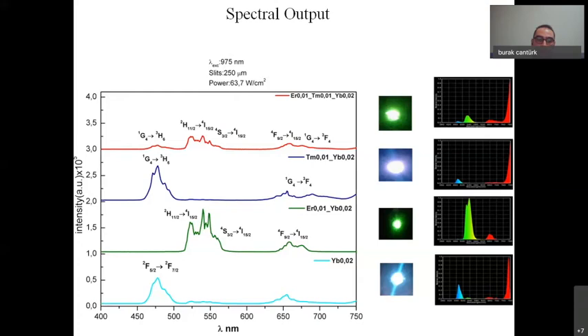As we can see from the figure, ytterbium here is responsible for the blue and red emission by itself. But if it's co-doped with erbium, we can see that it transfers its energy to erbium, acting as a sensitizer, and erbium is the activator in here, and the blue peak that comes from the ytterbium disappears in the end. And erbium is dominant and responsible for the green emission when it's co-doped. Similar cases occurred in the thulium ytterbium sample as well.